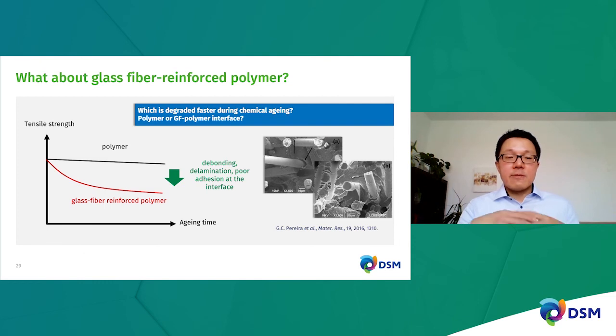And this reduction is manifested by debonding, delamination, and degradation of the interface. And this is already reported widely in the literature: if you look into the glass fiber interface with the matrix after aging, what typically happens is that there is some debonding between the glass fiber and matrix, such that the interface no longer carries load when we do some follow-up tensile testing. So something that we need to pay attention to.